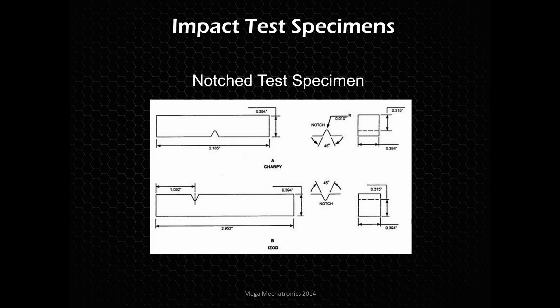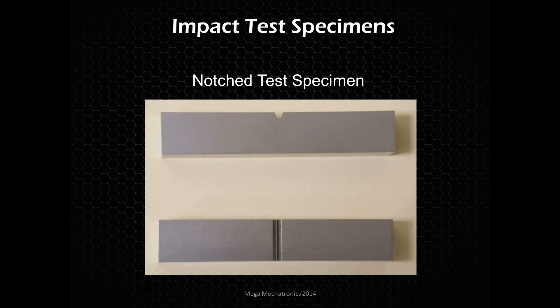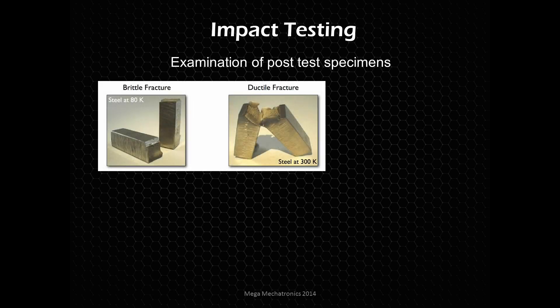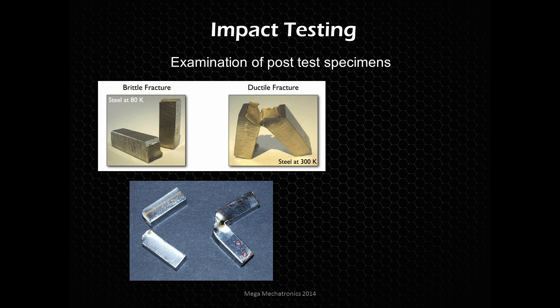Looking at the specimens, there is a notch in there. The Charpy and the IZOD are very similar — the IZOD is a little offset so one leg is longer, but dimensionally they are similar. Here's a close-up of a real Charpy specimen. We also want to examine the specimen after fracture. These two steels are the same composition at different heat treats — one shows a brittle fracture with less deformation, and the ductile fracture shows some deformation. The one on the right didn't even completely break, and the edges are rounded and folded up — it's plastically deformed and absorbs more energy.